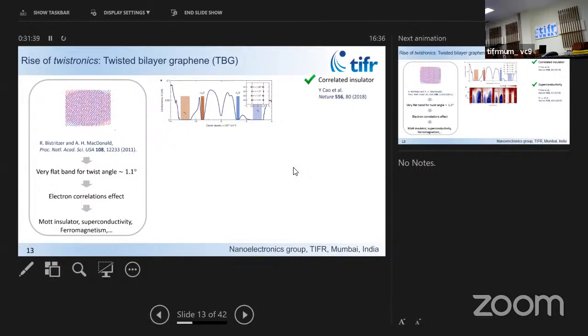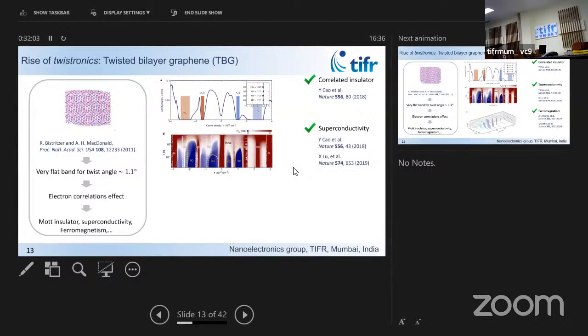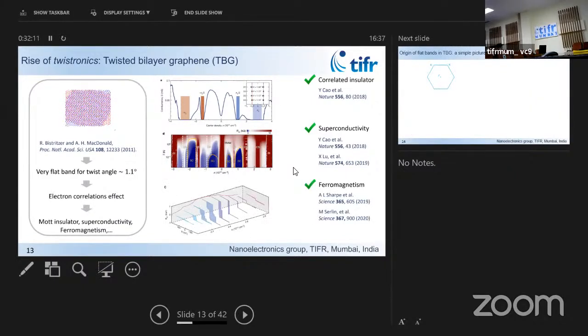Experimentally, people realized this by twisting layers of graphene. They could start with two layers of graphene and realize what is called a correlated insulator. It's all carbon, but it mimics materials that people have been studying for decades, which consist of other elements where electrons are strongly talking to each other. And not just that, it leads to superconductivity in something made only of carbon. No other superconducting material is there. Then magnetism: magnetism arising from just carbon seems like a very strange idea, but this magnetism has connections to the idea of topology, and is sometimes referred to as an orbital magnet. So it has given rise to a lot of excitement in the field.